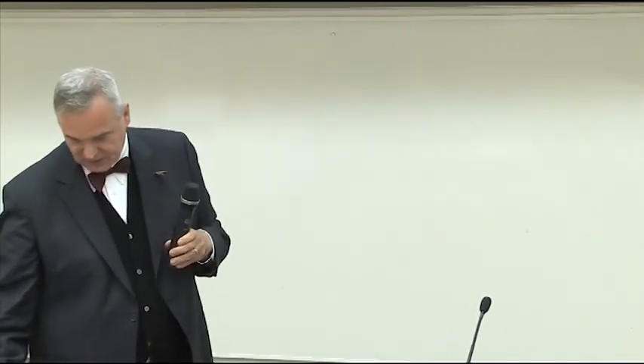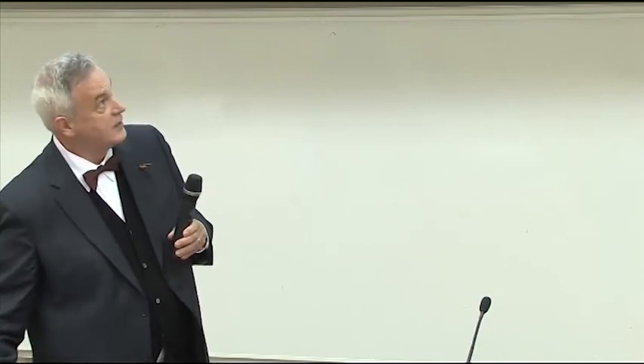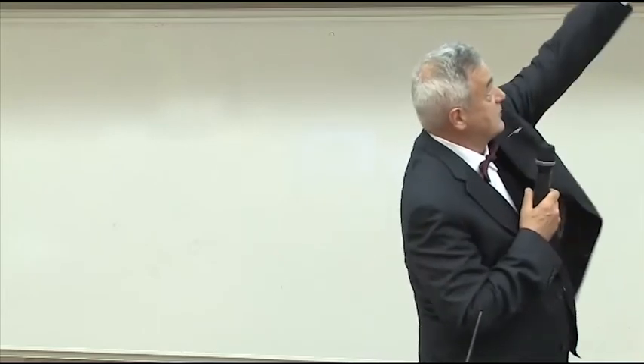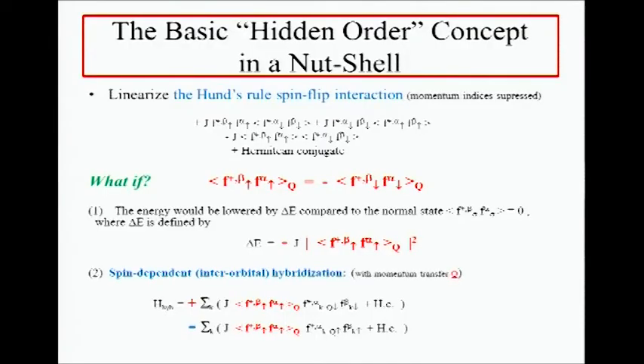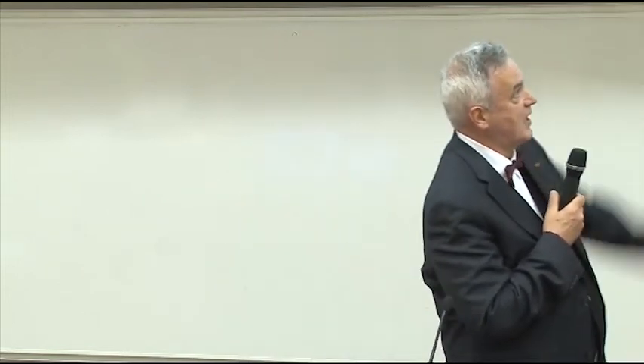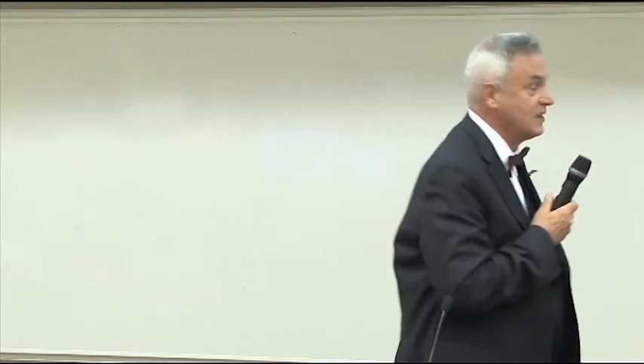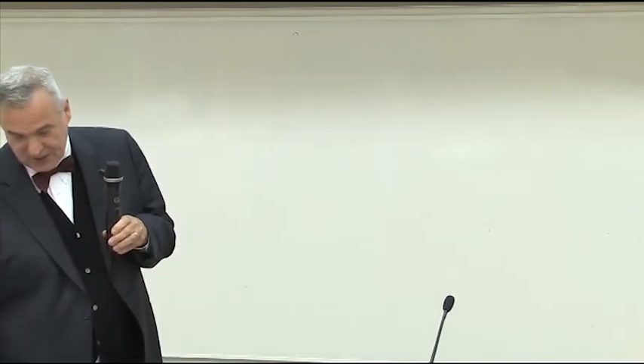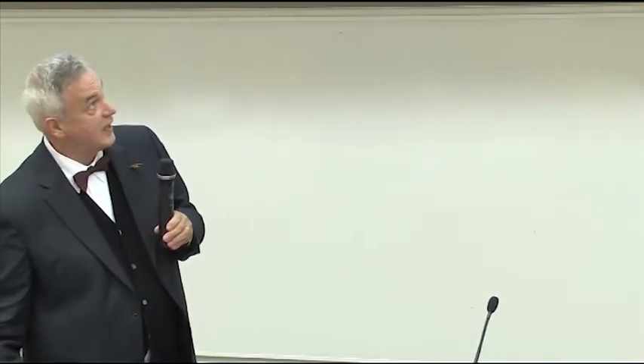This happens via mean field theory. If you take the Hund's rule expression and do the mean field type linearization of the interaction, you can ask what happens if the interorbital coupling for up-spin electrons is of opposite sign for the down-spin electrons. You get an energy lowering, and then a spin-dependent hybridization between these two different orbital bands, which breaks open a spin-dependent hybridization gap.